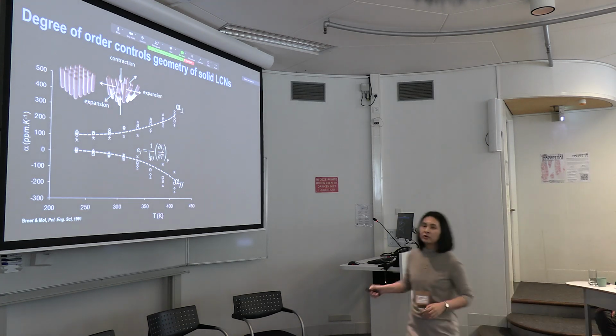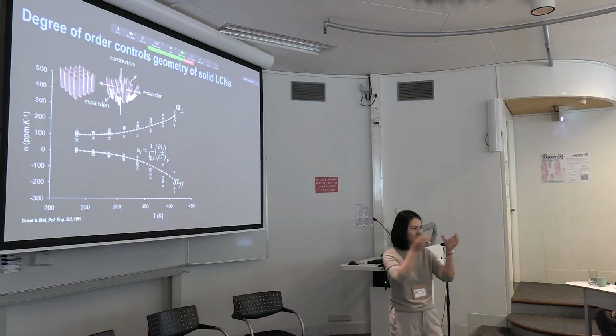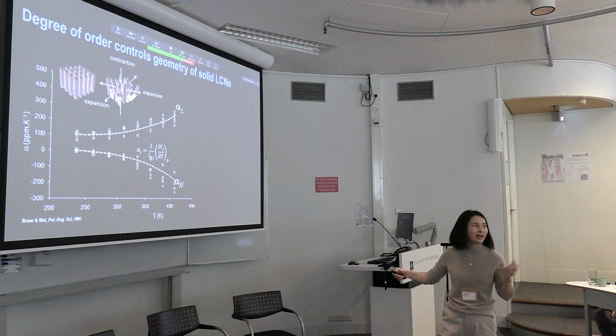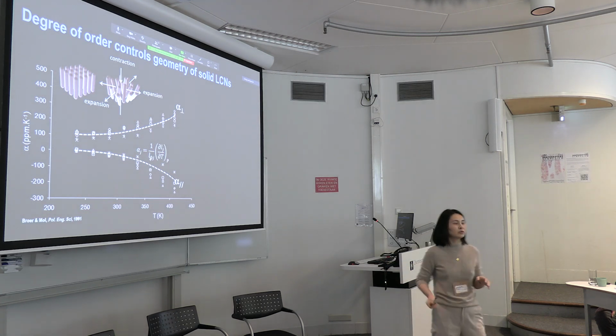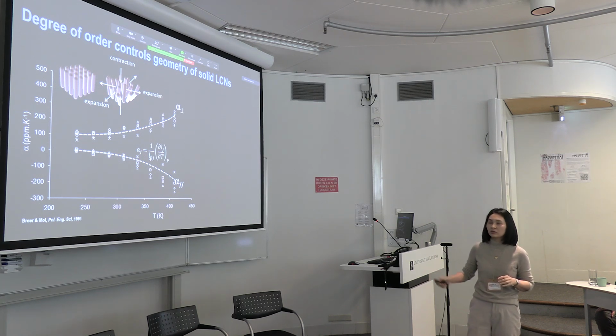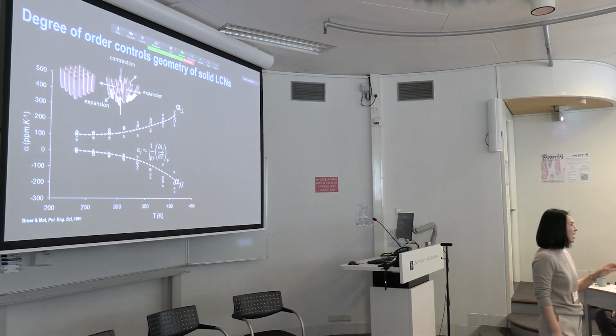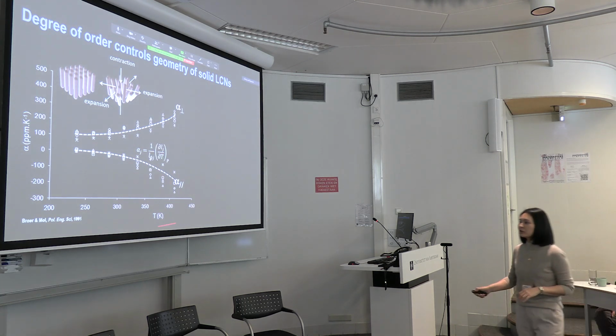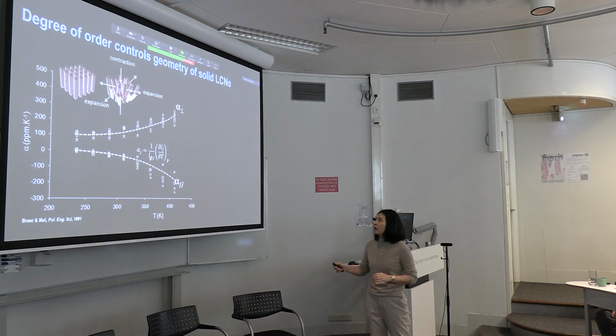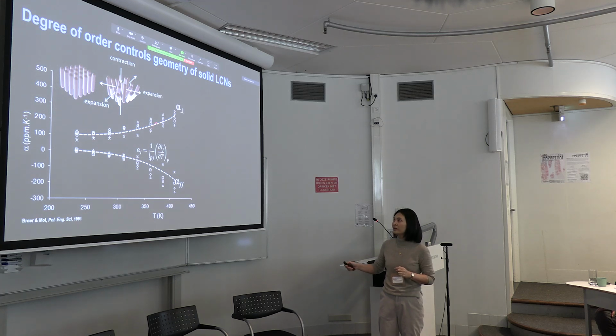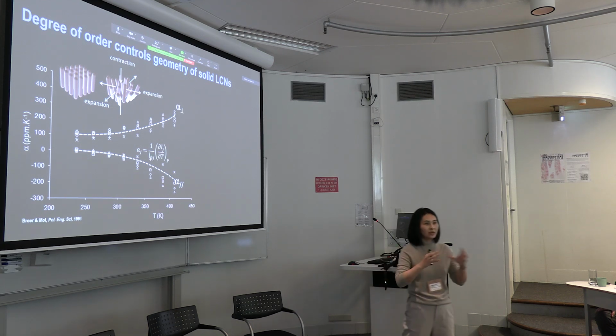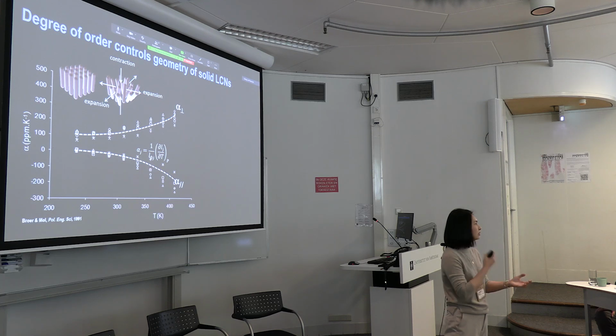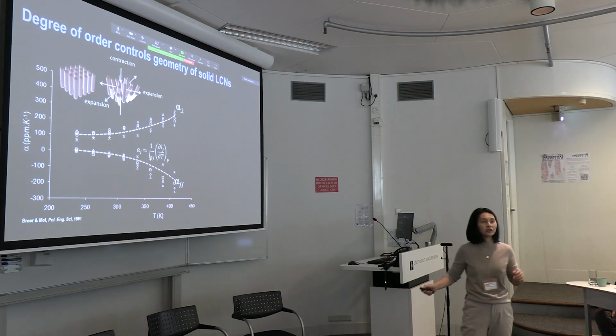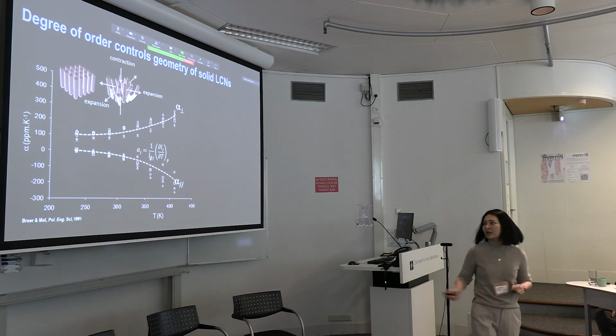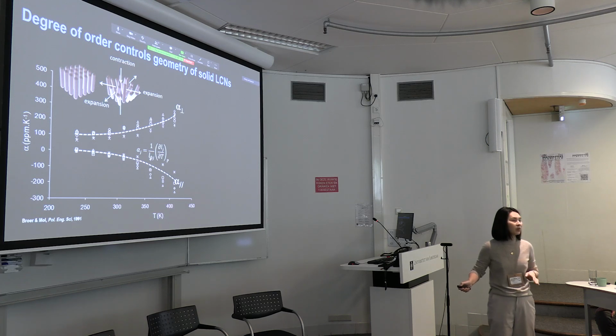What does that mean? First of all, you should think of this material, the molecule, like a rod shape, and if you bring them together, they are so-called very well aligned, so at a high order state. Once you start to decrease the alignment, so it is less ordered as you see here, what happens is that contraction and expansion happen simultaneously on the same material. So if you measure the thermal expansion coefficient, what you will see here is that perpendicular to the general molecular direction, the thermal expansion coefficient goes to positive, which means the material expands. That is your common knowledge. Every day you have the material, you heat it up, it expands. But with this material, when you measure the direction that's parallel to the molecular direction, what you will see is that the thermal expansion coefficient starts to decrease, and to a certain point it becomes negative.